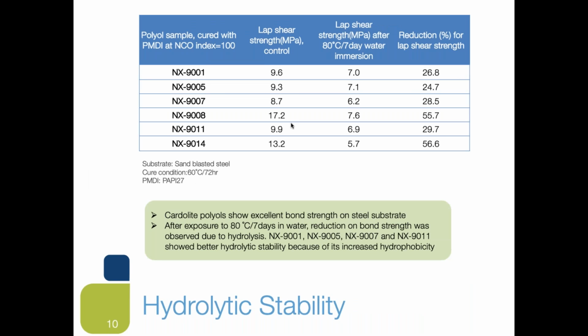When it comes to moisture resistance, we just talked about the moisture sensitivity study, but you also care about the hydrolytic stability, because many polyurethane links can experience hydrolysis, meaning the bond breaks, and therefore your ultimate mechanical performance, like adhesion strength, tensile, or hardness, could be reduced. So in this study, we studied polyols by measuring lap shear strength change for the hydrolytic stability. We collected the lap shear before exposure to water, and then collected another lap shear after exposing to 80 degrees C, 7 days immersion.